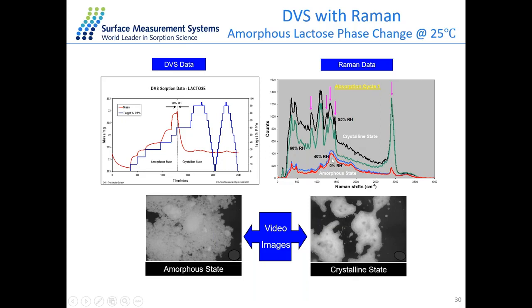We've also coupled it with Raman data. In this case, we're comparing 0%, 40, 60, and 95%. At the lower percentage RH in our amorphous state, we have a particularly different Raman spectra compared to our crystalline state here. The intensities are much greater, and we have a few peaks that were not there before and are there now. So we can actually monitor the change using Raman.